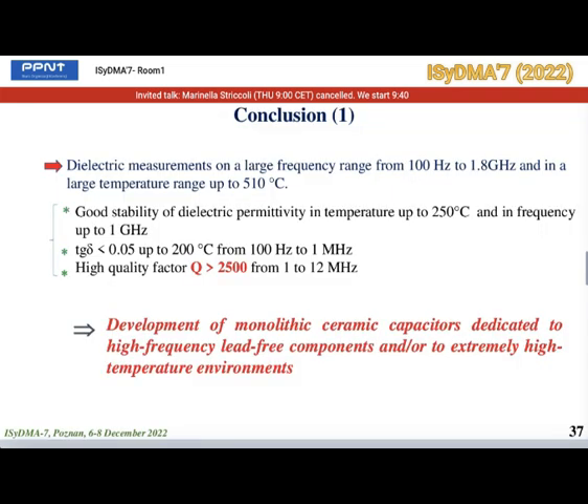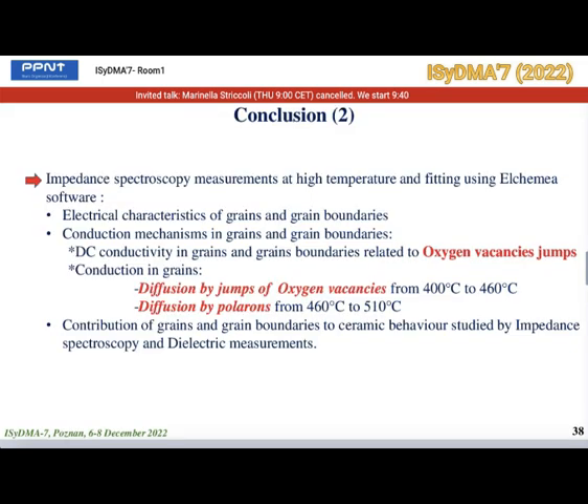In conclusion, we can say that SCT ceramic with 40% of calcium is a good candidate for the development of monolithic ceramic capacitors dedicated to high-frequency lead-free components and or to extremely high temperature environments due to the stability of its dielectric permittivity and its low dielectric losses over a wide range of temperature and frequency. Impedance spectroscopy measurements at high temperature and fitting using Elchemea software enabled us to study conduction mechanisms in grains and grain boundaries, as well as their electrical properties and contribution to dielectric ceramic behavior.